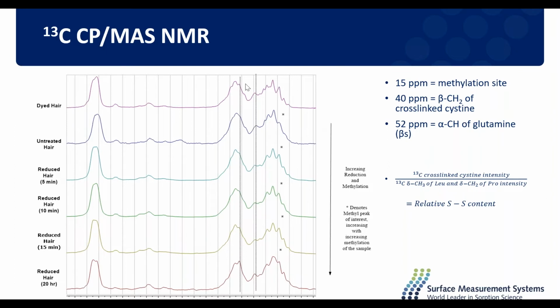I've highlighted some peaks here of interest. The first being this site, which has been starred. Now, this site is where we would expect to see a change in the peak due to the methylation of our disulfide bonds once we had reduced them. However, if you can see, the differences are not very clear. There's a slight increase, but there's not any significant changes that we might expect.